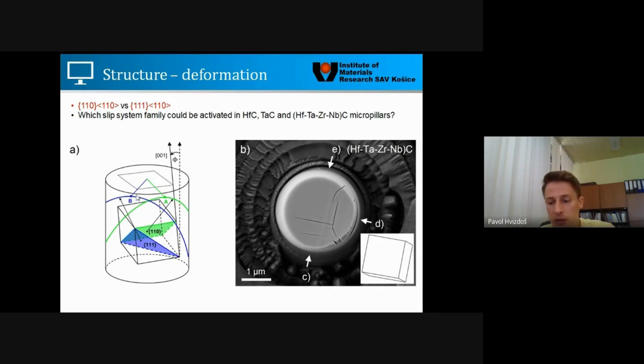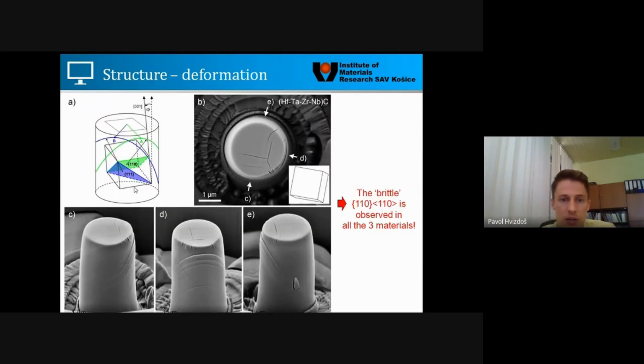We didn't do anything special. We just simply checked what the case is in our tests, and we got that this is the 110. We were very surprised, but that's the fact. In all cases, not just for the ultra-high temperature high entropy carbides but also for the monocarbides, it was unique that the 110 was activated. So we could confirm that 110 has lower critical resolved shear stress compared to 111.